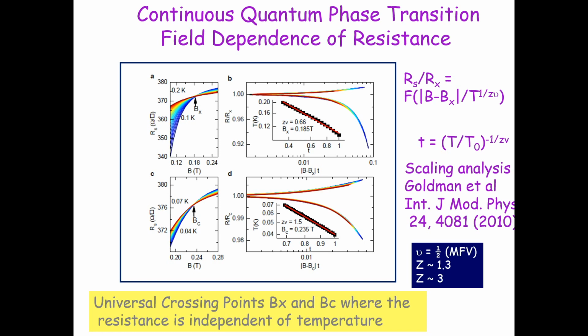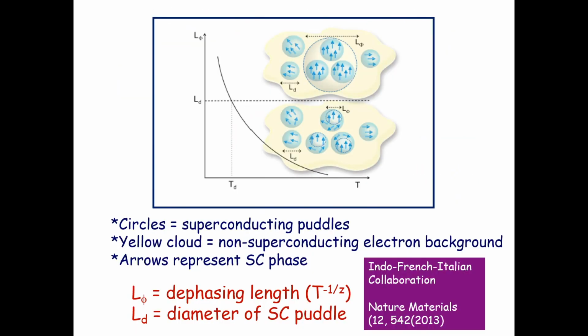And the explanation for that is we are going from the so-called clean limit to a dirty limit. And why that happens, that two carrier model becomes very important here to explain this. So, the picture that we have presented is this. We have a phase correlation length L sub phi, or the dephasing length, which goes as T to the power of minus 1 over Z. And so, it diverges as I go to lower and lower temperatures.